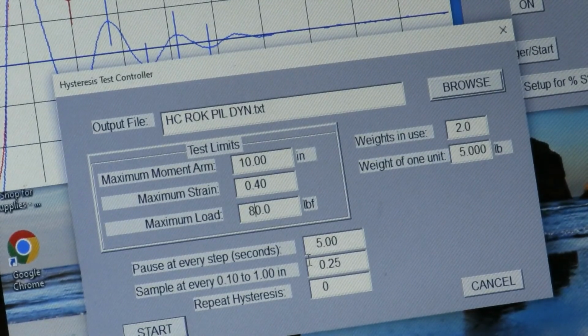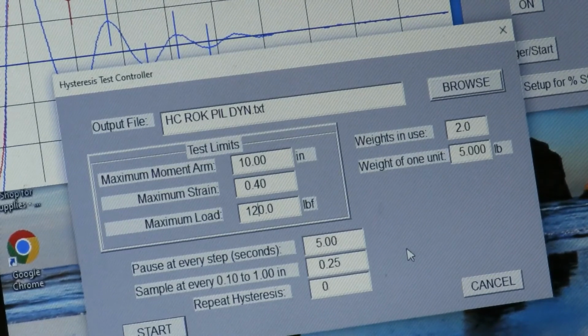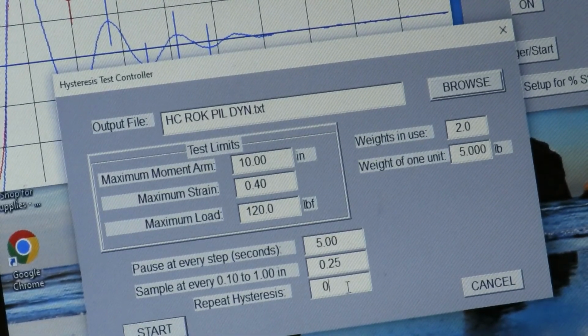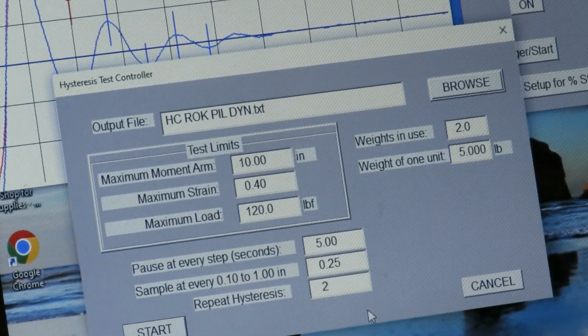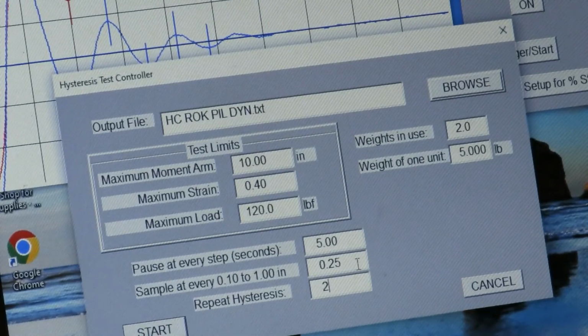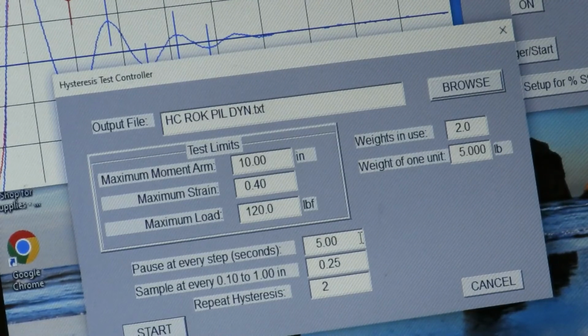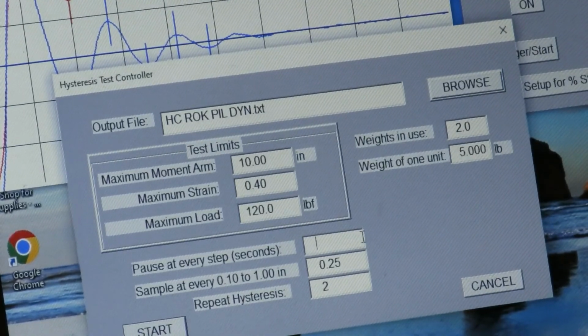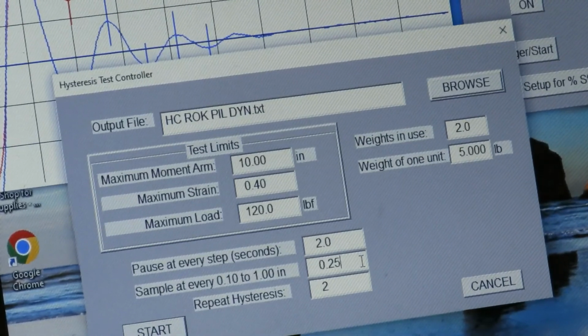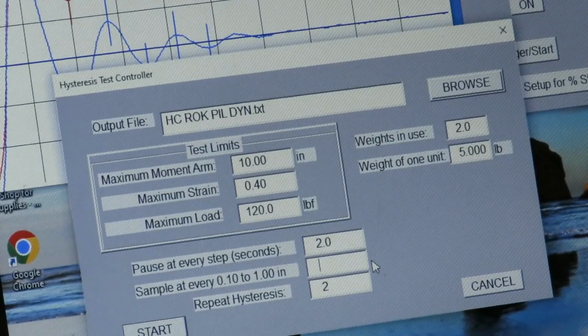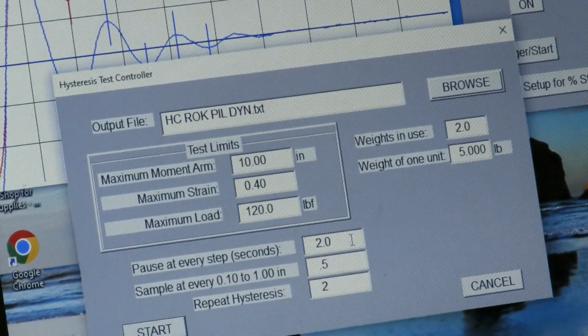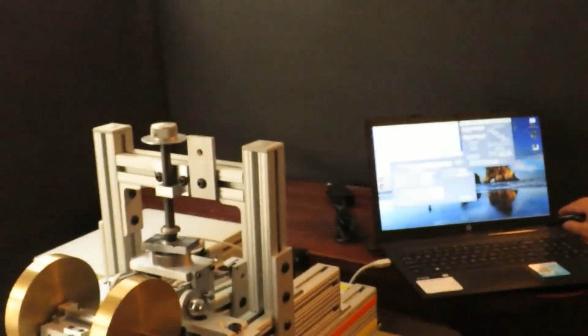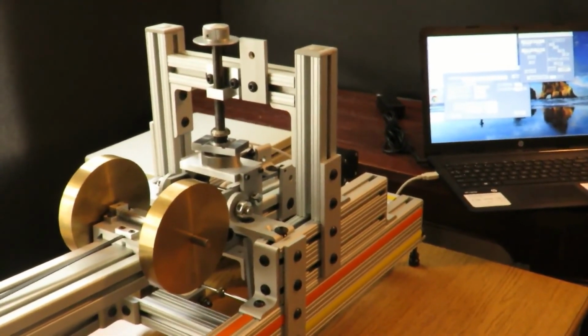Okay, we have the data input which says the maximum moment arm 10 inches, the maximum strain 40%, maximum load 120 pound forces, pause at every step of 5 seconds, sample spacing between 0.1 and 1 inches, in this case quarter inch. At this point we change to 2 seconds, stop, and the hysteresis repeat is 2. The weights are 2 and each weighing 5 pounds. Once we do that, we go back to the table and start the test. As we initialize, the test starts.